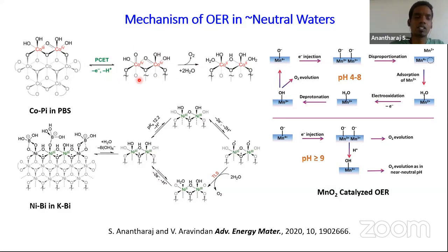And when this complex is formed, with the addition of 2 water molecules, this can evolve oxygen, forming the cobalt 2 complex. On another cycle of anodization, it will form this complex again, and this process will go on. And similarly, we have nickel. Nickel is also found to undergo such oxidation, because initially it will be in the 2+ oxidation state, then it will convert into the 3+ oxidation state, and it can follow any of these paths to evolve oxygen. And we also have manganese, which performs different paths of mechanism depending on the pH at which water oxidation is carried out. So these are the mechanisms in neutral water.